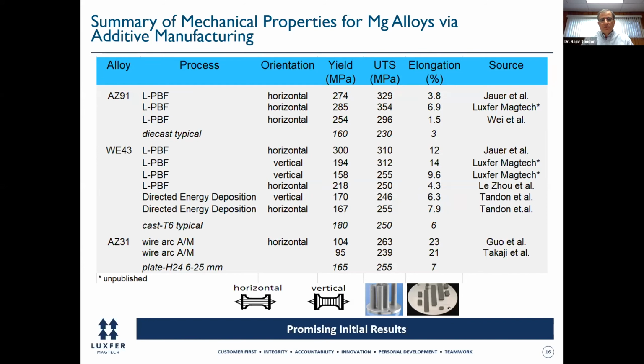Same thing with WE-43, which is one of the most investigated alloys. When you look at your cast T6 typical of 180 and 250 with an elongation of 6%, some of the best results show that you can even achieve extruded properties, such as reported by Jauer et al. from Fraunhofer. And then in some of our own work, we've clearly demonstrated that you can get yields close to about 200 megapascals with UTS, in some cases exceeding 300 megapascals. There have also been some properties reported with AZ31 with a wire arc process, and I'm sure Stefan is going to be speaking about this in the next talk. So clearly, there are promising initial results, and we hope to capitalize on this for at least some of the emerging applications.